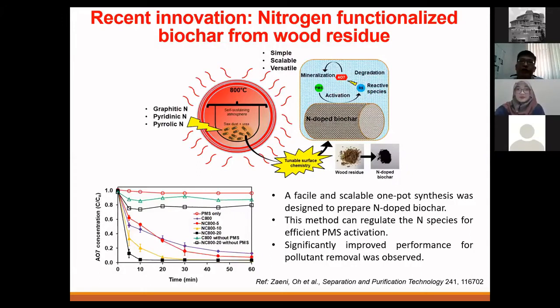So if you look at the previous presentation slides, we use the pyrolysis method under the flow of nitrogen gas or inert gas. So we did some thinking, and we feel that if we want to scale it up, it will be quite difficult because we need to continuously flow in the nitrogen gas. And we came up with something more scalable. We take it from the synthesis of graphitic carbon nitride, whereby a lot of people use something to encapsulate the precursor, close it very tightly, and then calcine at high temperature.